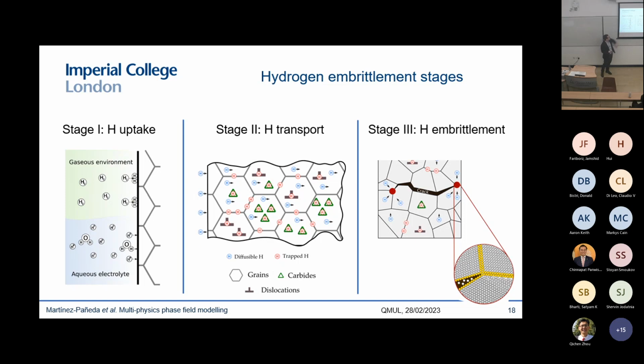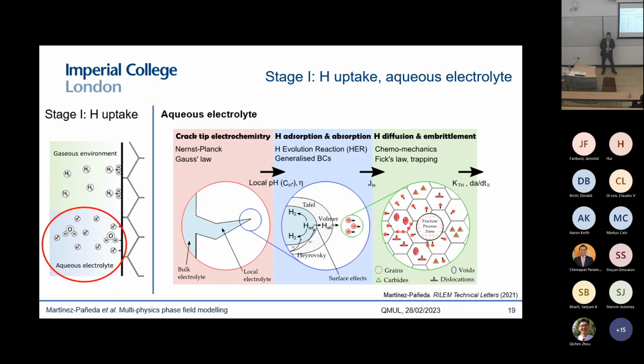And regarding the hydrogen uptake, for the case of gaseous hydrogen, at least for steady state conditions, this is relatively well understood. We have closed form solutions like Sieverts' law that we can use to understand what is the hydrogen concentration at the surface for a given hydrogen pressure. What is much more challenging is to predict what happens when you have an aqueous electrolyte. Because there basically you have all the elements of the hydrogen evolution reaction that you need to solve on the surface of the metal. And this is also very sensitive to the electrolyte behavior. So you need to solve the electrochemistry of the electrolyte to be able to predict the hydrogen uptake.